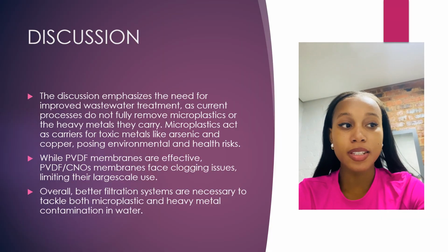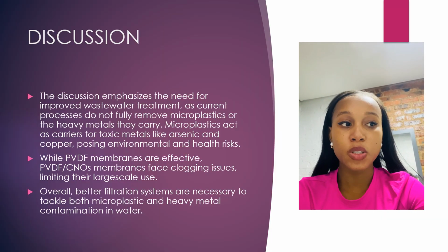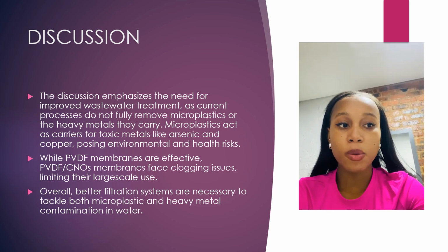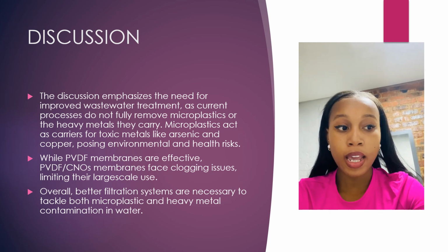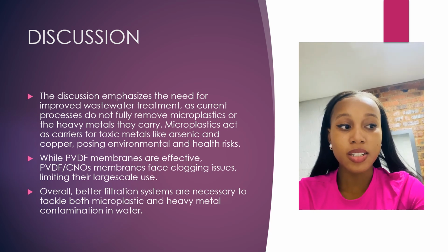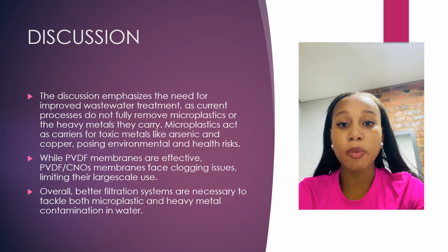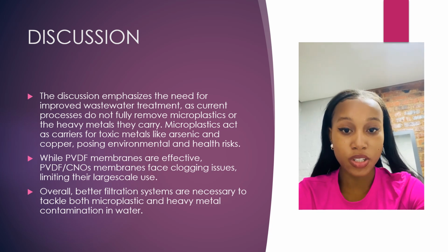The discussion emphasizes the need for improved wastewater treatment, as current processes do not fully remove microplastics or the heavy metals they carry. Microplastics act as carriers for toxic metals like arsenic and copper, posing environmental health risks. While PVDF membranes are effective, PVDF and CNO membranes face clogging issues, limiting large-scale use. Overall, better filtration systems are necessary to tackle both microplastic and heavy metal contamination in water.